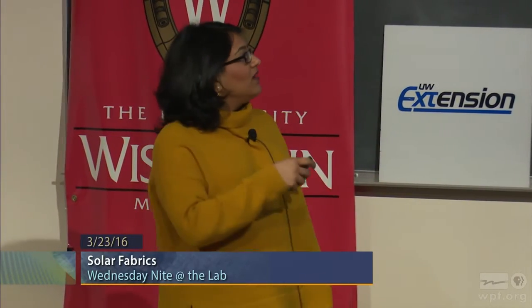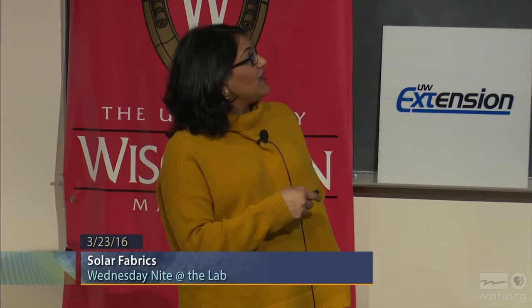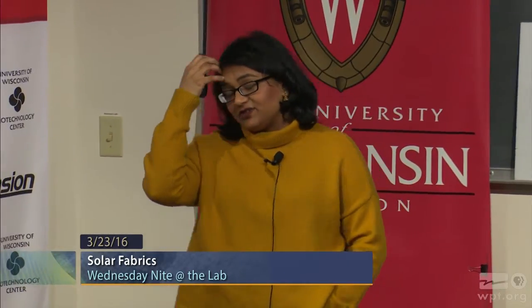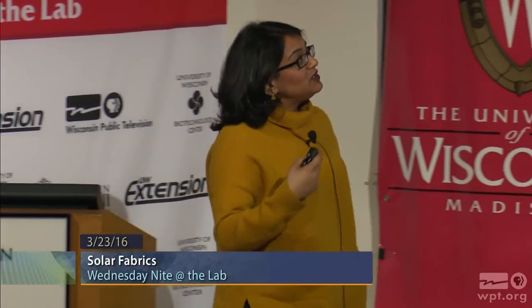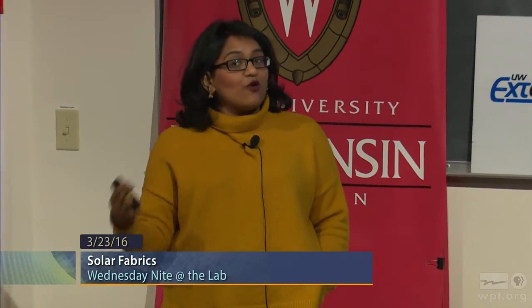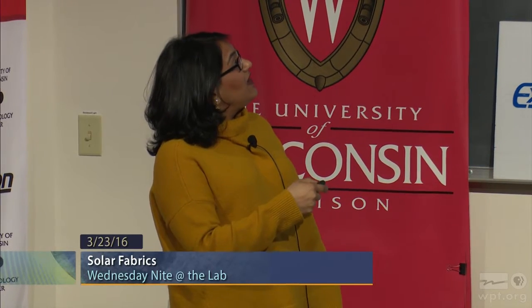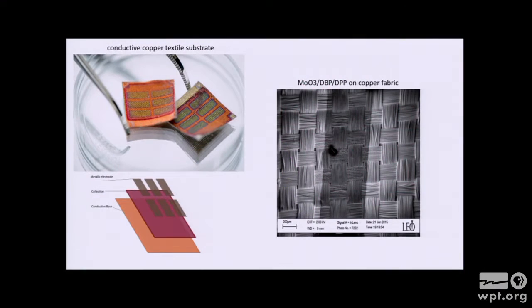So now we have our bottom conductive base. We can either use a copper fabric or we could use the PEDOT coated stuff that I talked to you about before. We have our photoactive materials. If we use organic compounds, they can actually also coat the fabric itself. And then on top, the last bit, our last electrode that completes our device, these squares here are a transparent metal or transparent material, called indium tin oxide. We can also end up using some metal vapors like silver and actually complete our device.